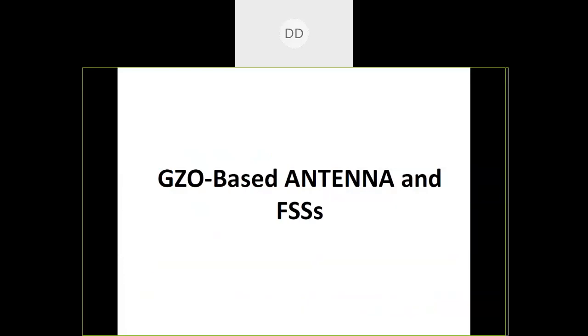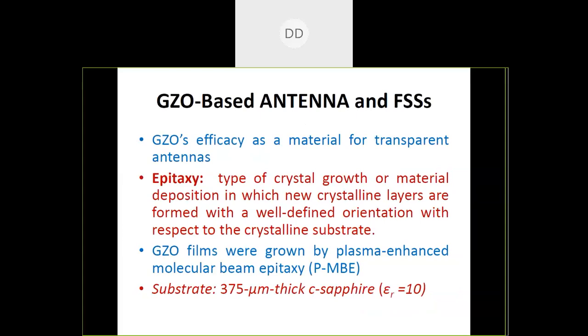antennas. So now we'll go through one case study of designing antennas and frequency selective surfaces using this gallium doped zinc oxide. The main purpose of this experiment was to study the efficacy of gallium doped zinc oxide as a material for transparent antennas. Here the epitaxy technique is used for developing the films. Epitaxy is a type of crystal growth or material deposition in which new crystalline layers are formed with a well-defined orientation with respect to the crystalline substrate.